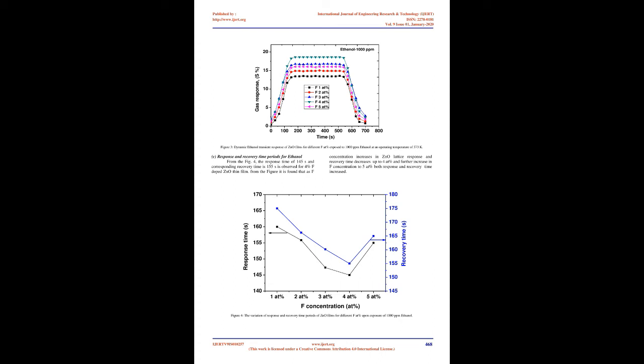Fig. 2 represents the sensing characteristics of the F-doped ZnO film as a function of ethanol concentration in air at different F%. It is observed in the figure that as F concentration increased, the response increases rapidly in the lower concentration region of ethanol, while it increases gradually at higher concentrations of ethanol. For a low concentration, 250 ppm, there is a smaller surface coverage of ethanol molecules on the film and hence the surface reaction proceeds slowly. On an increase in gas concentration to 1000 ppm, the surface reaction increases due to a larger surface coverage of ethanol molecules, resulting in a rapid increase in response.